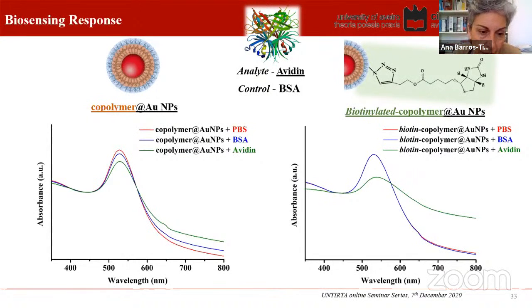So as you can see, this functionalization strategy worked, because whilst in the presence of the copolymer gold nanoparticles, avidin didn't really cause any major shift of the surface plasmon absorbance, and it was essentially equivalent to what could be seen in the presence of BSA, the control protein. These are due to the medium changes, but not really molecular recognition at all.